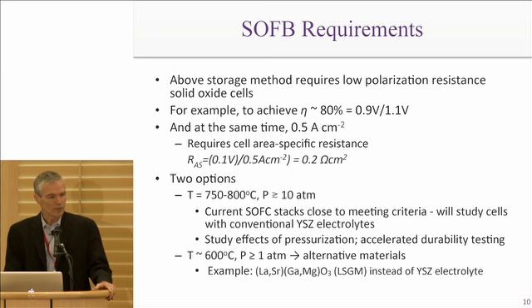And we have the two options for doing this. One is more normal SOFC operating temperatures, but pressurizing. Okay? And this is a range actually where we think fairly conventional SOFC stacks are very close to meeting this requirement. And the other one is a lower operating temperature device that could operate more like atmospheric pressure. But here we need some alternative materials, non-conventional materials. For example, a typical SOFC has a zirconia electrolyte. That doesn't have a high enough conductivity at 600 degrees centigrade, so we're starting to use some alternative higher conductivity materials.